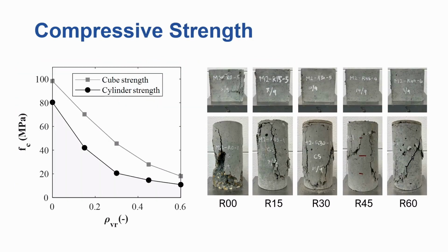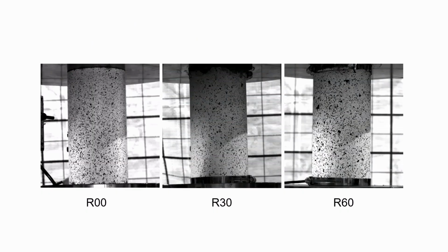And these are the results for the compressive strength. So on the y-axis, I'm plotting FC, the compressive strength in megapascals, against rho VR, which is the rubber replacement ratio in percentage. And these are the results for the cube and cylinder compressive strength. And as the rubber content in the mix increases, the compressive strength reduces, which makes total sense. Rubber is weaker than natural aggregates, and the more you have of it in your concrete, the weaker it becomes.